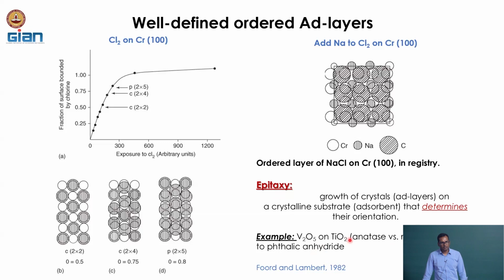It is the same titania, but now I have an anatase phase versus a rutile phase, just because the surface structure is different. The vanadium oxide, which is the active material for this reaction, has grown on the surface differently because of the different surface nature, and that results in a different activity.